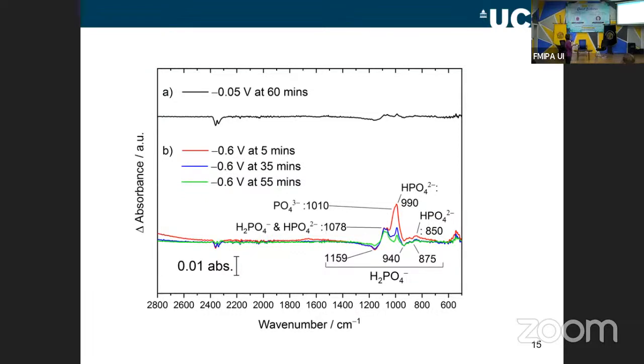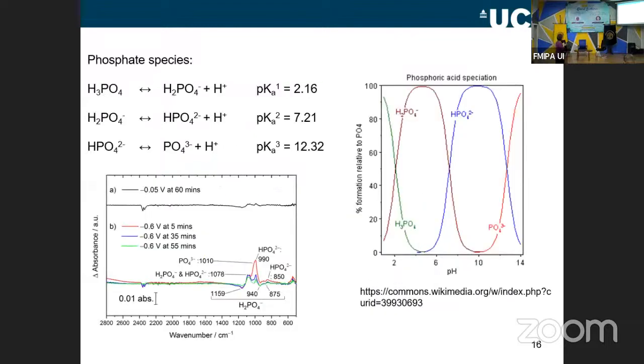So the important thing really is, if you look at the spectrum that's in red, so this is at early times, we get a big peak that goes up that's due to phosphate. And also we get an increase due to HPO4 2-, and we get a decrease that's due to H2PO4-. So we've got more phosphate, more HPO4 2-, and less H2PO4- during this process. So what's happening? So let's remind ourselves about the different phosphate species that are present in phosphate buffer solutions.